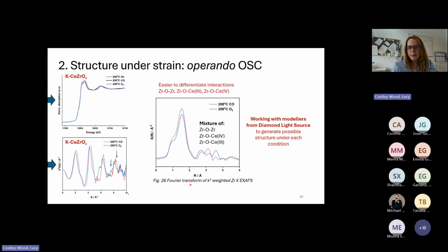In the Fourier transform, in the second shell, these materials are quite difficult, and it's very difficult to assign all of this, particularly because the cerium paths and the zirconium paths are completely destructive. So we're losing a huge amount of intensity here. So we're now working with modelers from Diamond Light Source, and they are generating some structures that this material could be sitting in under the different conditions, which we can then apply to our data.